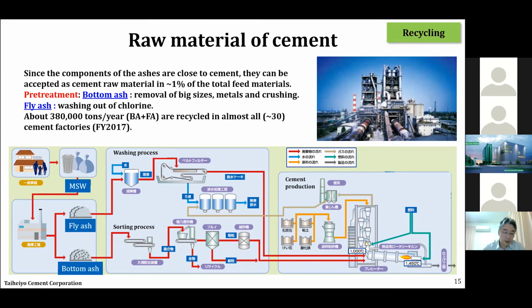Furthermore, pre-treatment for bottom ash and fly ash is required. In the case of bottom ash, removal of big sizes and metals and crushing is necessary. And in the case of fly ash, washing out of chlorine is required. About 380,000 tons per year are recycled in almost all cement factories over Japan.